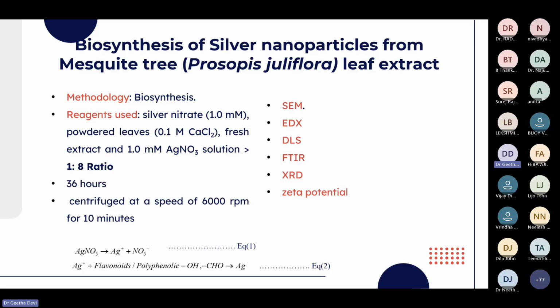It was taken in the ratio 1:8, and the reaction was carried out for 36 hours, and it was centrifuged at 6000 rpm for 10 minutes to get the product. And the product was dried, and it was used for the characterization, and the characterization methods employed are SEM, energy dispersive X-ray analysis, DLS, FTIR, XRD, and zeta potential.